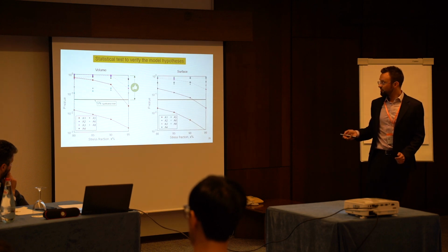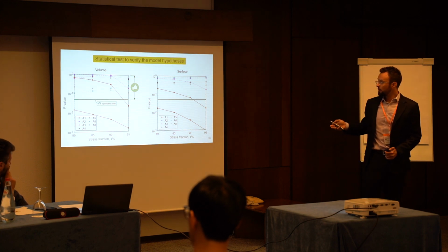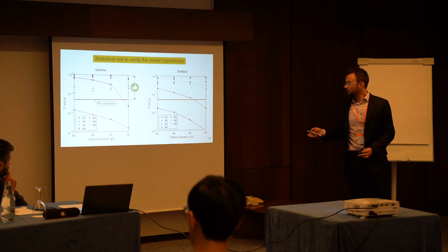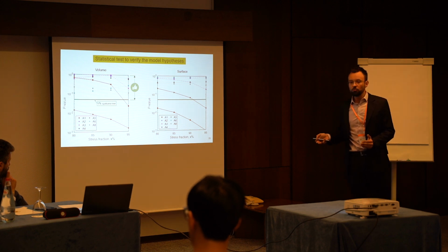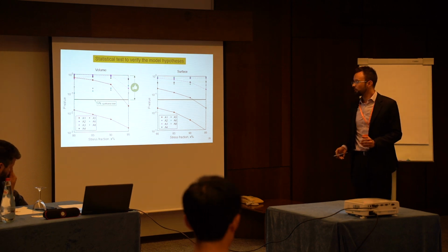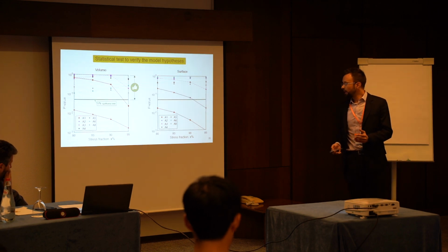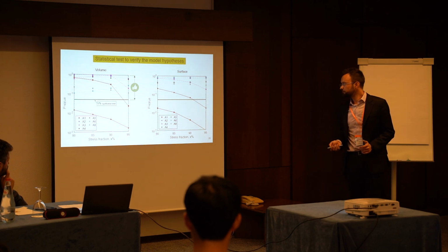And in the case of surface, using this statistical test, we have A1 below A5 series. So, due to these low values, below 5%, we didn't consider the joint analysis, for example, A1 volume and A5 surface. We neglect both A1 and A5 from now on.